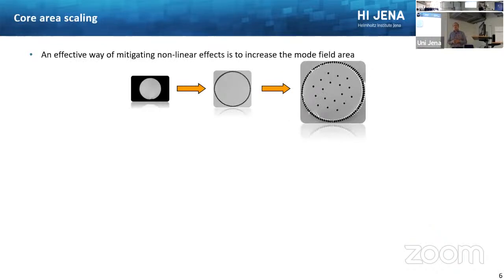The other possibility you have is to increase the diameter of your waveguide. In the top picture on the left side, you see a standard telecom fiber with this very small dot in the center. This is your core of a few microns. And using different technology, which I will talk about later, we have managed to increase the diameter of this fiber, up to the right side, to multiple 10 micrometers.